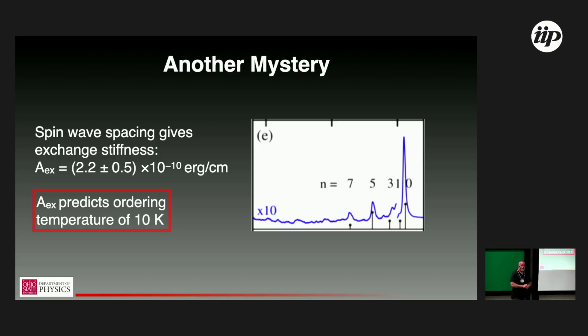This also comes with another mystery, though, and this is, in fact, sufficiently mysterious that at least I didn't fully realize this was surprising for a couple of years working with the system. So this is now zooming in on the experimental data in blue, and you can see these very clear magnon resonances. We fit out to 7, but you can see there's likely even more excited state, complex higher order behavior there. And those black dots represent analytic calculations of where the thickness quantized spin waves should lie. So the agreement's quite good, and you can use that to extract an exchange stiffness for the spin wave. Basically, how much energy does it cost to rotate my spin as I move along the wavelength of the magnon? And so we can extract that number.